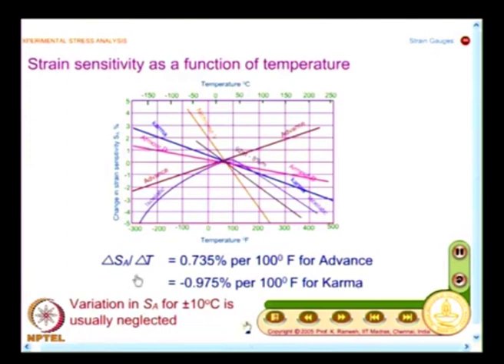So, what you find in quantitative terms is change in the strain sensitivity of the conductor as a function of change in temperature is 0.735% per 100 degree Fahrenheit for Advance, it is minus 0.975% per 100 degree Fahrenheit for Karma. So, you have this data, it is possible because strain gauge is constructed based on a conductor. So, I need to know the conductor property, then I need to look at when I make it as a loop how does this change. So, what we will look at is handling temperature information and segregating the change in resistance due to stress applied and temperature change is the most challenging aspect in strain gauge instrumentation.